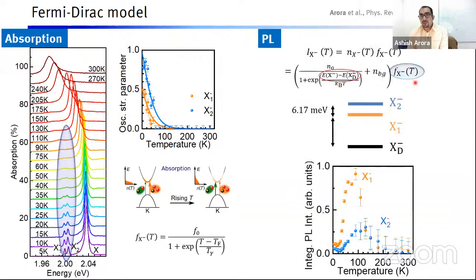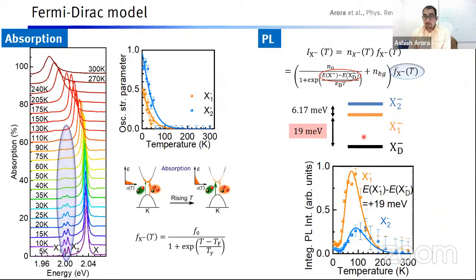We can fit these two curves with this oscillator strength function, and they fit very well when we assume that there is a dark trion state 19 meV below the bright state. Therefore, in the tungsten disulfide monolayer, the dark trion is the lowest energy state by 19 meV, which is what gives rise to this integrated photoluminescence behavior. In fact, this was confirmed very recently in another work by a direct measurement of the dark trion energy by some magneto-optical techniques.